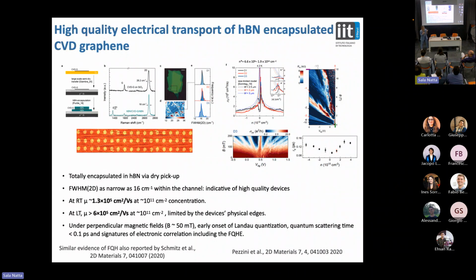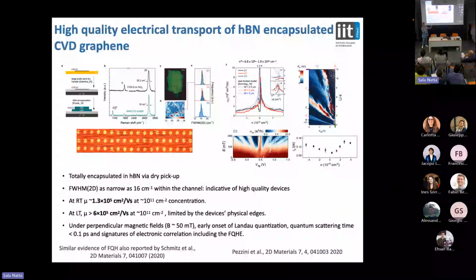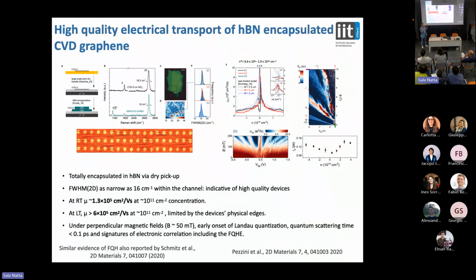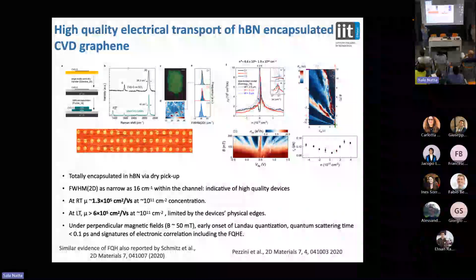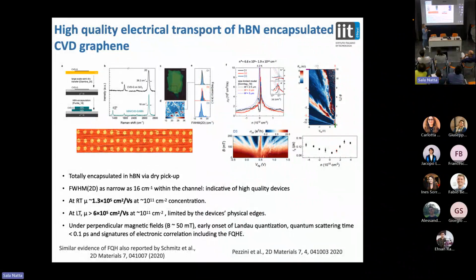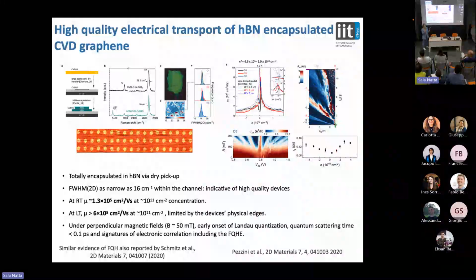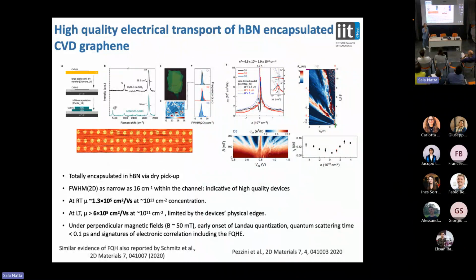They were 600,000 until 3 years ago for exfoliated graphene, the one with the Scotch tape, the one of the Nobel Prize. But these synthesized bottom up, no way, it was never so good. But a couple of years ago, we demonstrated that it is identical. So nowadays, if you use the exfoliated material or you use the CVD, chemical vapor deposition, the technique we adopt, the bottom-up one, it is the same, okay? So basically, you don't have the difference anymore. That's when I say the material is now mature, because now the properties are as they should be, and you could start proving some of the things that you have read in books, and you might think they are bullshit.